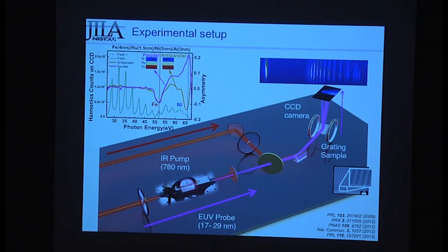This is the type of signal. The dashed and dotted lines are just a static reflection from a magnetic material as we use a pair of Helmholtz coils to change the direction of the magnetization. And then we calculate the magnetic asymmetry, which is the change in the magnetic moment normalized, so we have a background-free signal.